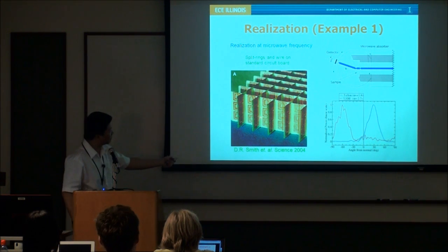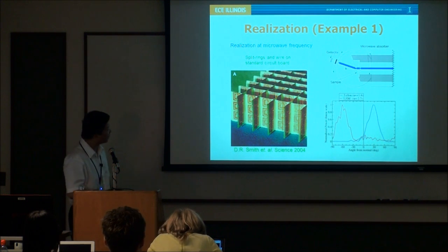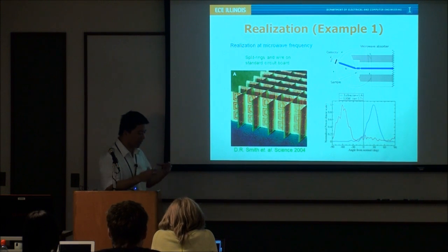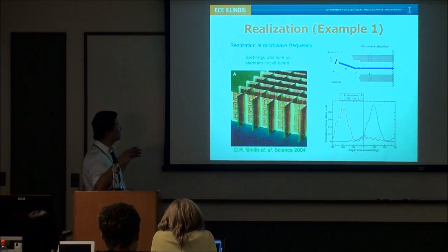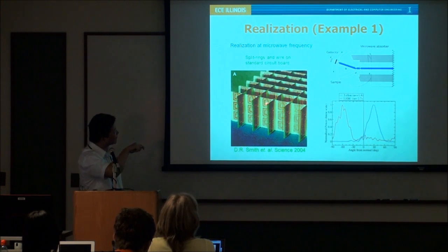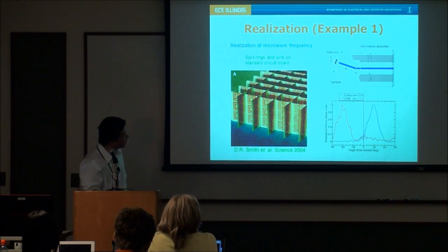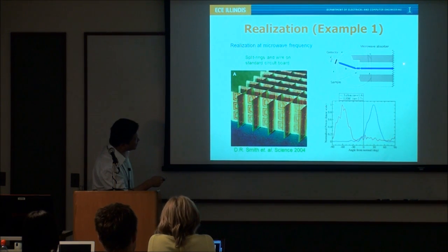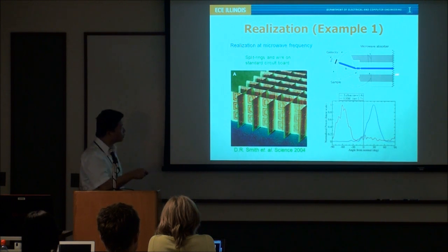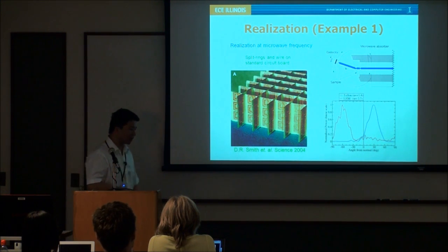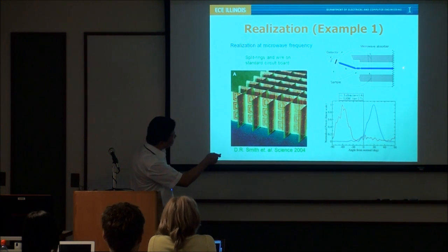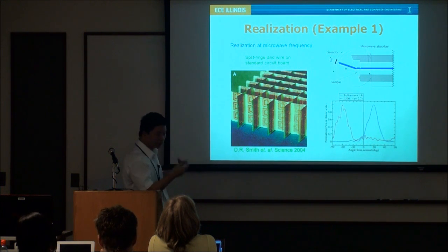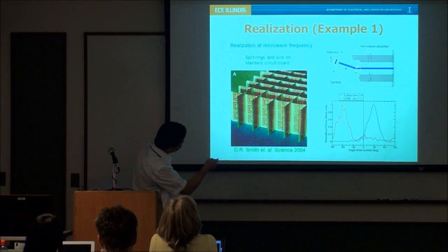So that's why people can use this. They use plastic, which people use to make a PCB, printed circuit board, and print copper split rings on the surface and construct that into a three-dimensional circuit board. Then people place that device on top of sample holders. And if you have a microwave source passing through this sample, what you will see is, instead of a positive refraction, let's say you have a microwave propagating along this direction. For a normal, natural material, well, this is a normal line, okay?